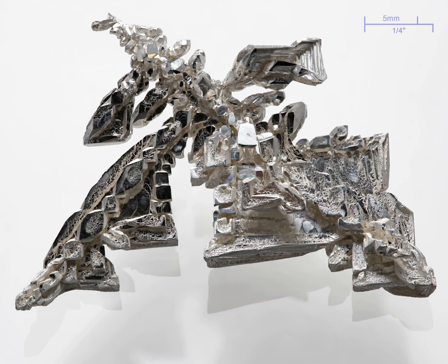Silver does not react with air, even at red heat, and thus was considered by alchemists as a noble metal along with gold. Its reactivity is intermediate between that of copper, which forms copper oxide when heated in air to red heat, and gold. Like copper, silver reacts with sulfur and its compounds. In their presence, silver tarnishes in air to form the black silver sulfide.